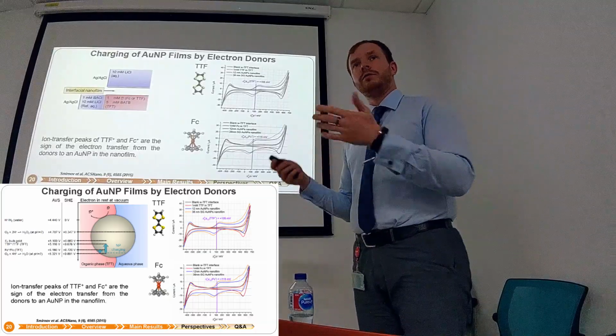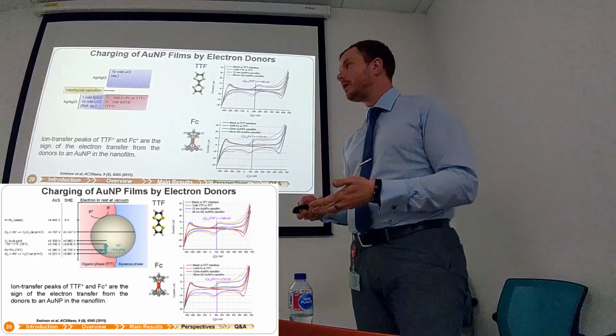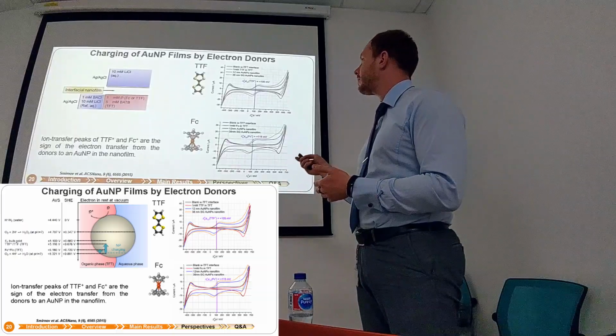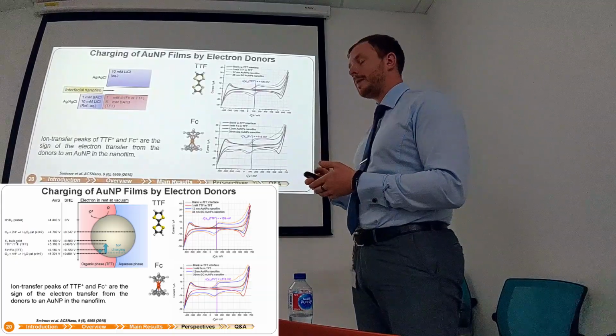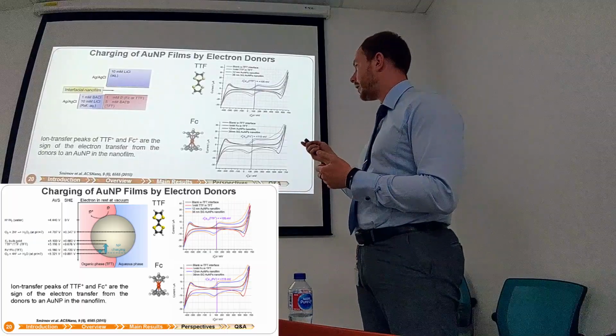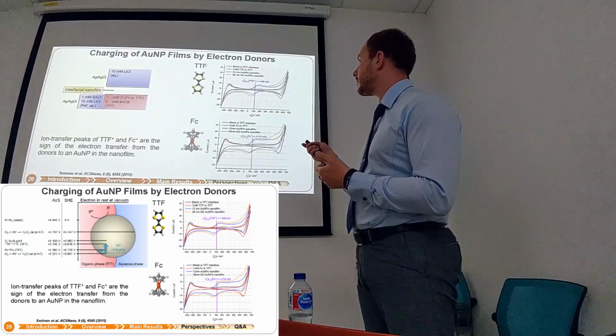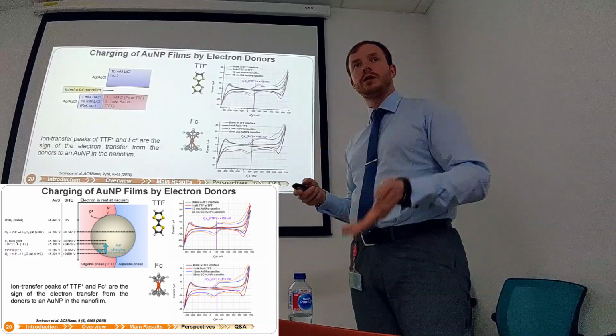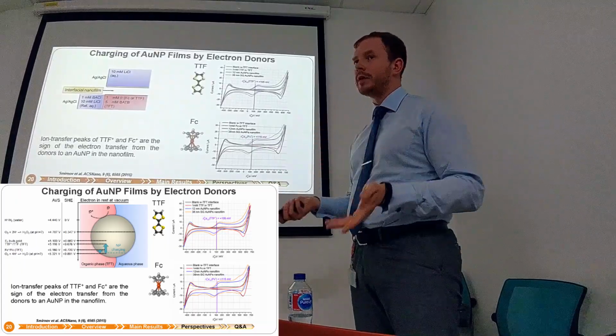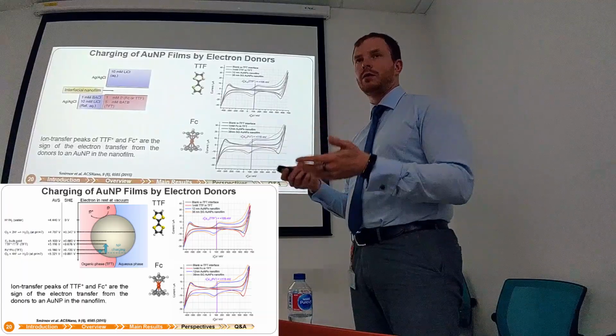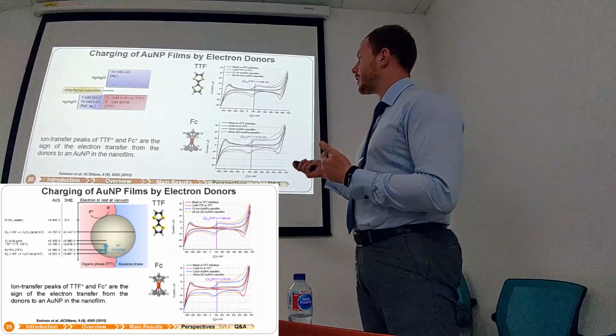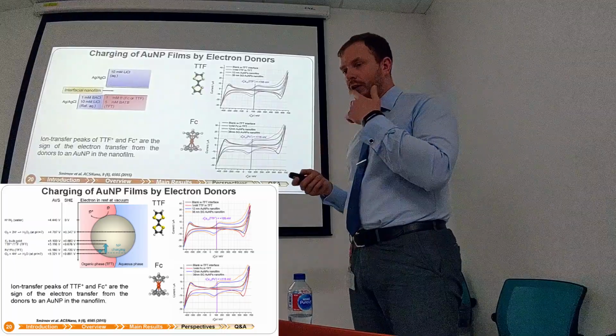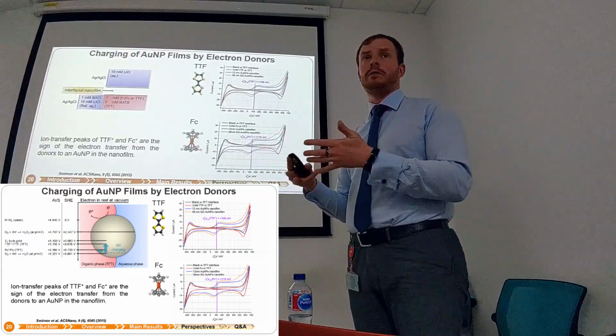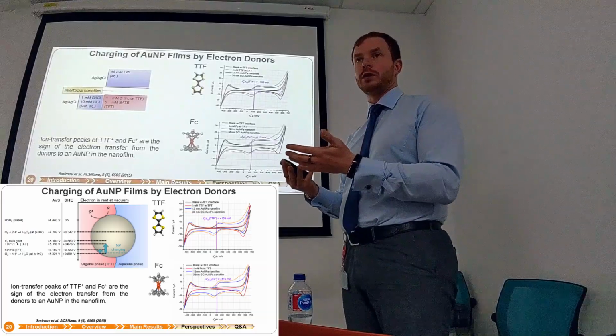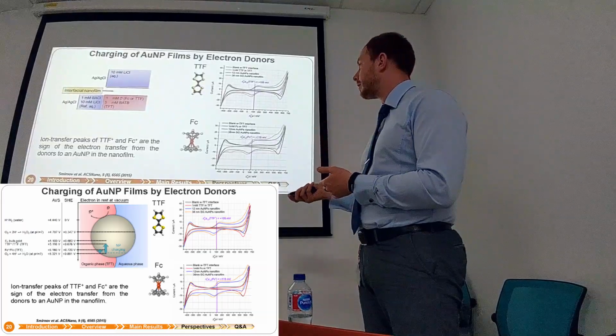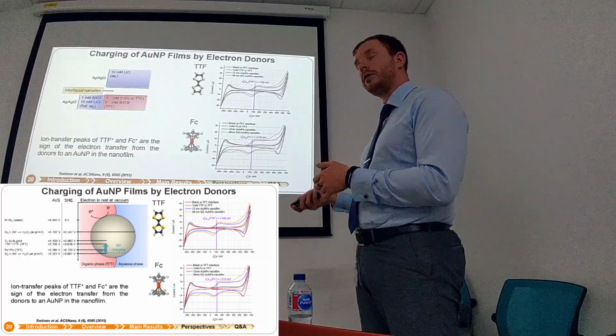And of course, as we started to work with TTF, the first candidate was TTF. We did it without TTF. Then we added the film, added TTF, and surprisingly we saw some peak. It means that something is crossing the interface. Again, it might be electron, it might be ion, who knows. But then we shifted to ferrocene, which has about the same electrochemical potential as TTF in the organic phase. And for ferrocene we saw more or less the same.